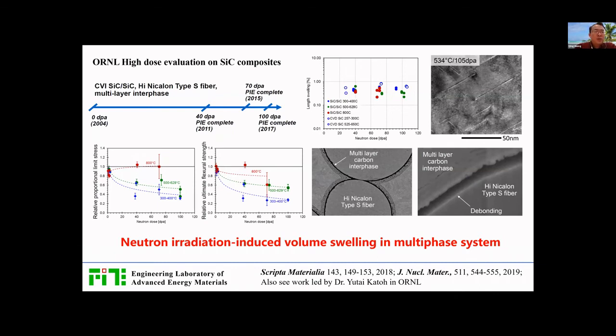Now, silicon carbide fiber reinforced silicon carbide composite is one of the promising candidate materials for fuel cladding. However, neutron radiation induced volume swelling always happens within the multi-phase systems due to the difference in crystallinity of silicon carbide fiber, interphase, and matrix. So the swelling mismatch among them leads to enormous cracks, which is the reason for a drop of strength as well as thermal conductivity under neutron irradiation. So our problem is, can we find a new candidate for this interphase to resolve this serious problem?